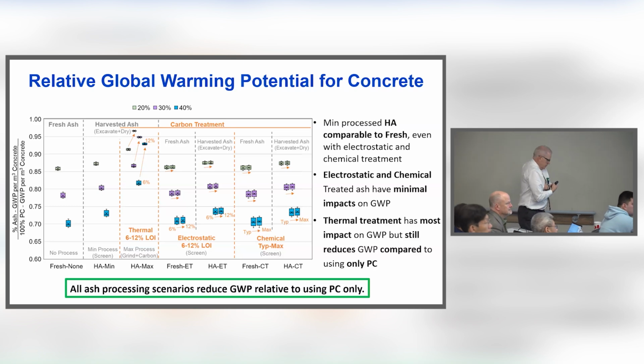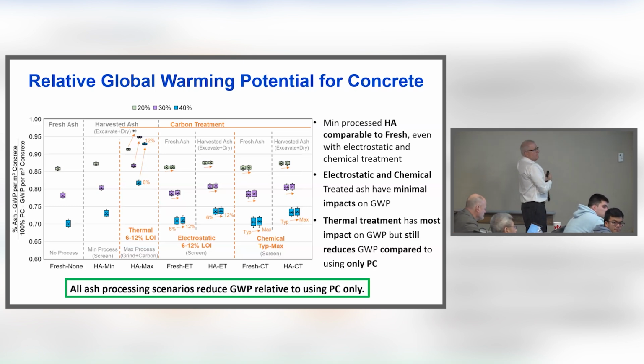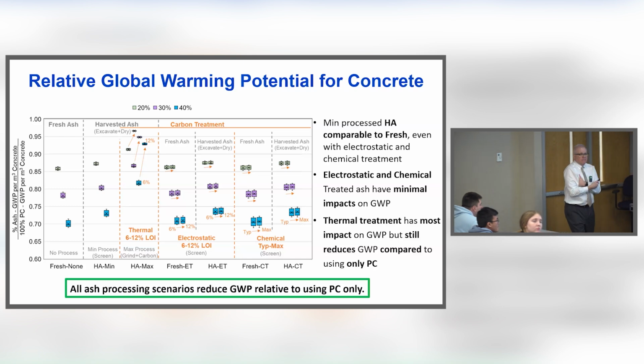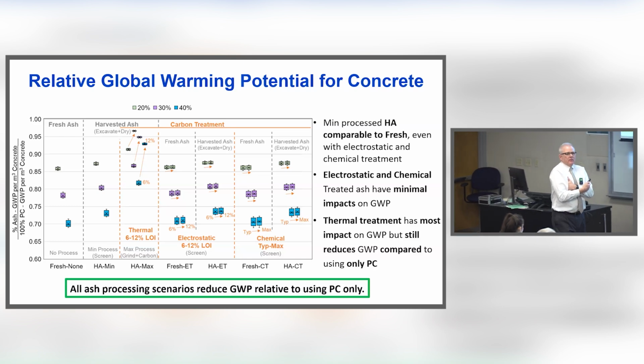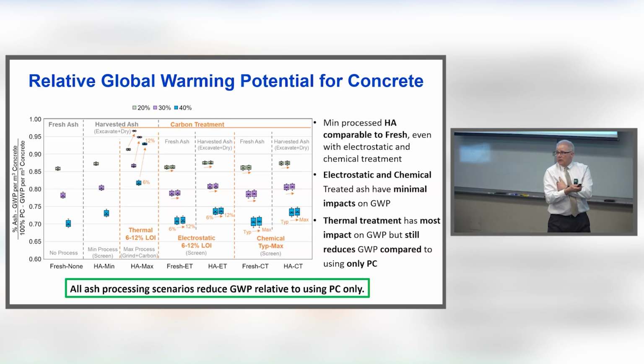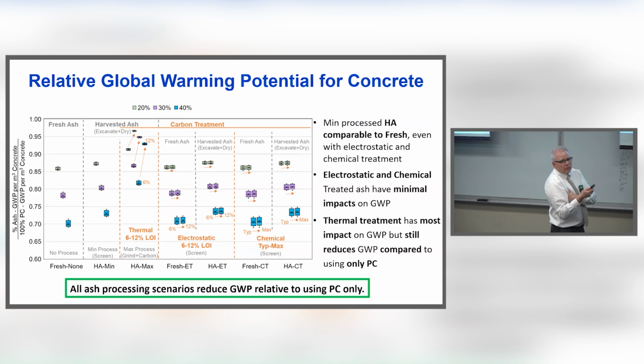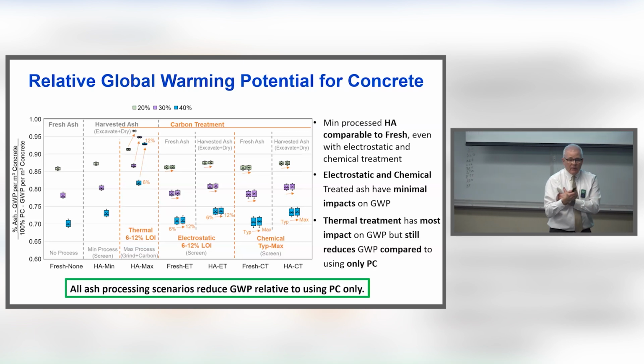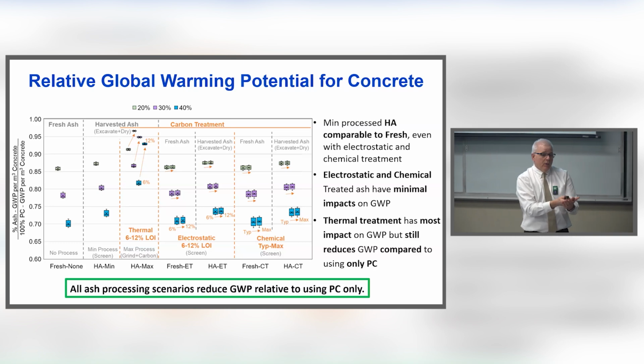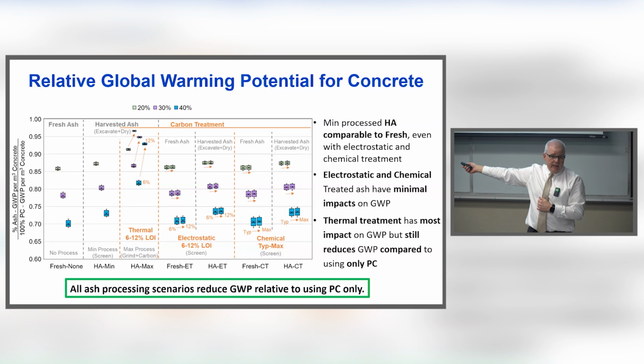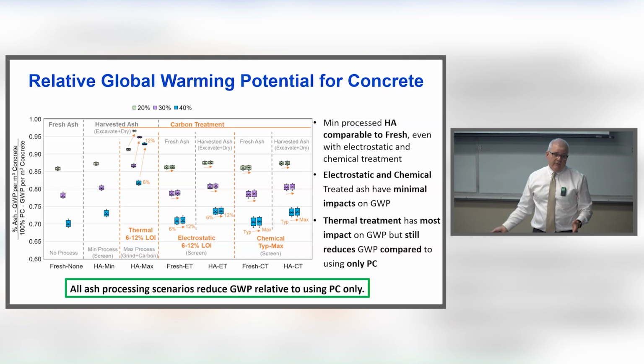Yes, sir? So are you using bottom ash in this study, or is this ASTM class C? What type of fly ash are you showing this for? Yeah, this is a fair question. The question is, am I using fly ash alone or bottom ash or both? And we've made 2 assumptions. One, we've got commingled ash. We will grind that to meet the particle size criteria in ASTM C618. And we will use ash that meets the chemical composition requirements in C618. So I've made that assumption, all right? If it doesn't meet that, it's out, all right? So we're assuming it has that basic set of properties.